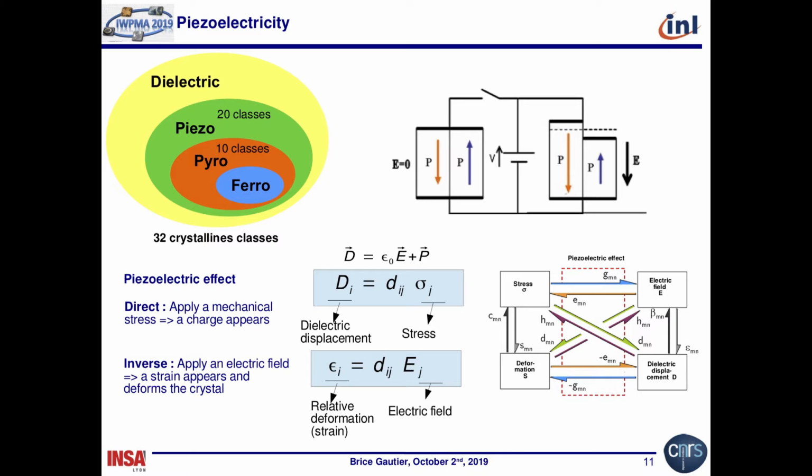So if you want to image ferroelectricity, you will rely on piezoelectricity, namely the inverse piezoelectric effect. Anytime you apply a difference of potential between the tip and the sample, you will have a deformation of the material due to the converse piezoelectric effect. This is the contrary to the direct piezoelectric effect, where you have a charging due to a mechanical force.